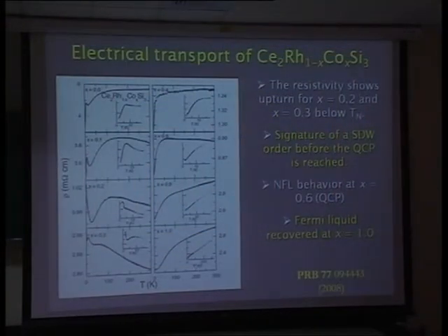This system has been studied quite extensively. It forms this AlB2 structure. If you have Ce2RhSi3, which is this compound, it's antiferromagnetic. You can place this at the peak of the Doniach phase diagram, and slowly you substitute cobalt at the rhodium site, and you see the TN goes down in temperature. At a certain temperature range, TN is very close to zero, and you have this spin density wave kind of formation, a kind of jump in resistivity.